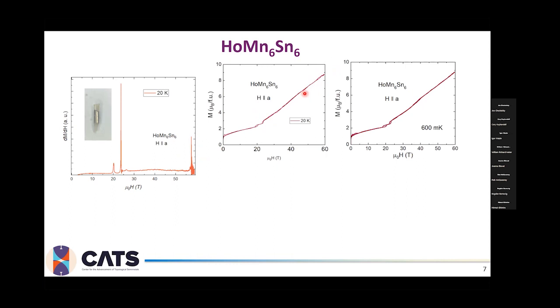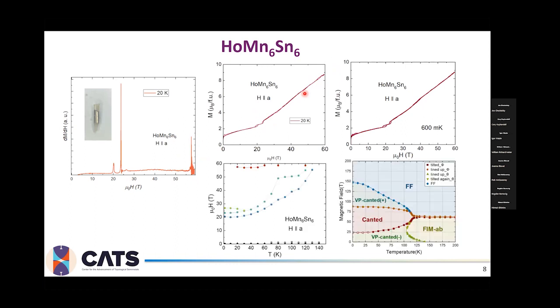By making many curves like that at different temperatures, we are able to form the phase diagram of this material for the A direction, and we can see that it works pretty well with the theory, with the transition going around 25 Tesla. However, we do see some smaller phases, which are most likely coming from the same transition but from different growth of the domains. We can also pick up some of the higher transitions, which might reflect that one. It is just that experimentally we may be observing this at a slightly smaller field.